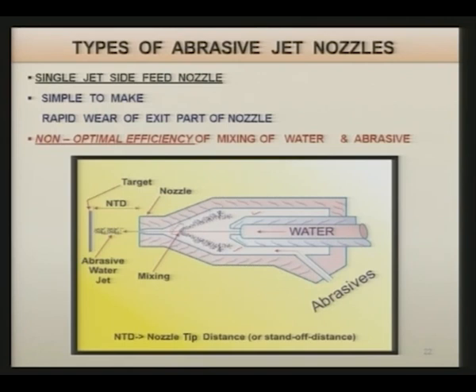After mixing they are going out, and you can see on the outer side abrasive particles are there and in the middle water jet is there. So, abrasive particles are coming directly in contact with the inner surface of the nozzle, so wear of the nozzle will be more. You can see the distance between the bottom face of the nozzle and the upper face of the workpiece is the nozzle tip distance, and when this abrasive water jet hits the workpiece surface, the removal of the material takes place.